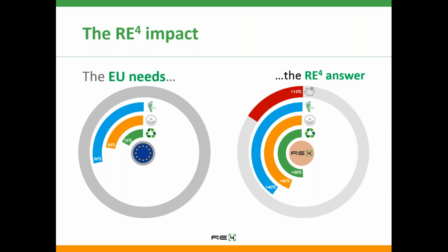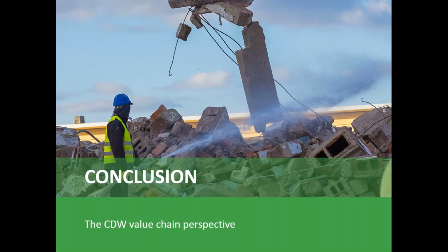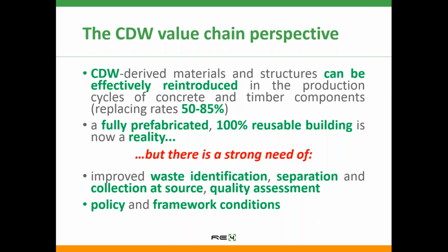We've also provided an additional impact, an economic impact, because the RE4 solution resulted to be more than 50% cheaper than conventional solution. So to conclude, the RE4 project has demonstrated how CDW derived materials can be effectively reintroduced in the production cycles of concrete and timber components with a replacement rate of 50 to 85%. Moreover, from a technical point of view, a fully prefabricated 100% reusable building is now a reality.